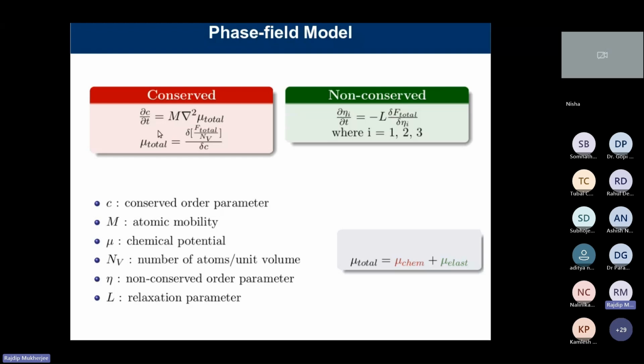So this μ total, this chemical potential, is the variational derivative of F, the Gibbs free energy, with respect to composition. And there is a non-conserved field variable, like I told you, for order-disorder transformation, grain growth or solidification. You have a non-conserved order parameter which describes the microstructure, related to the Allen-Cahn equation, where η is a non-conserved order parameter, L is the relaxation parameter related to the kinetics, and F total is the free energy, right?